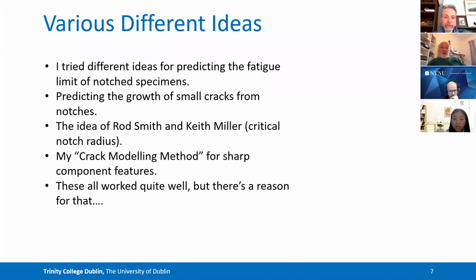So at the time, I was knocking around various ideas that were in the literature for predicting the behavior of notches, such as predicting the growth of small cracks and whether those cracks became non-propagating or continued to propagate. An idea of Rod Smith and Keith Miller that was around at the time was that if the notch is sharp enough, it has a critical radius and you can pretend that that notch is a crack. That was useful, and I was able to implement that on components by making some modifications, what I call my crack modeling method. So that was beginning to work for components as well.